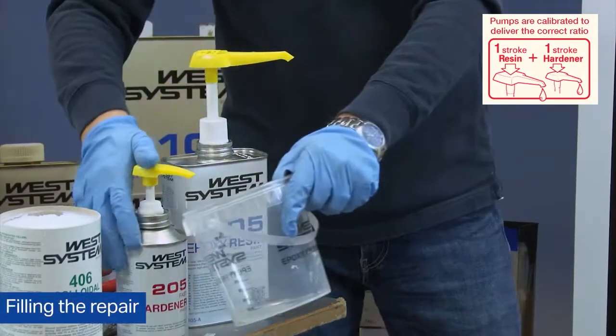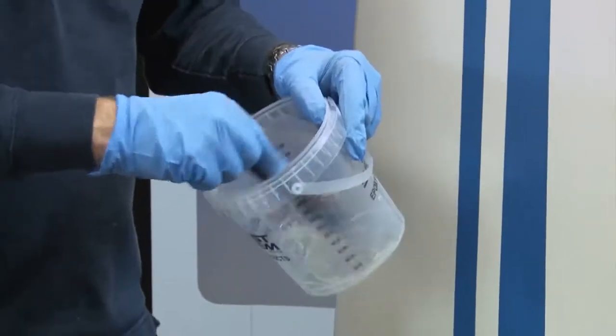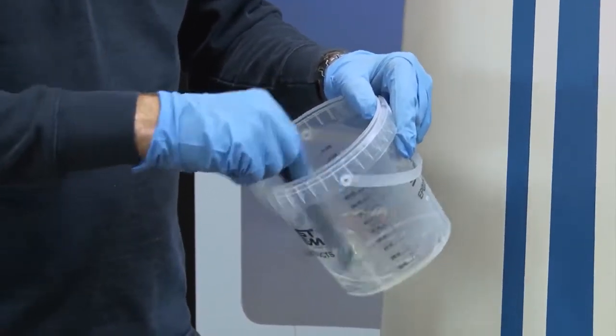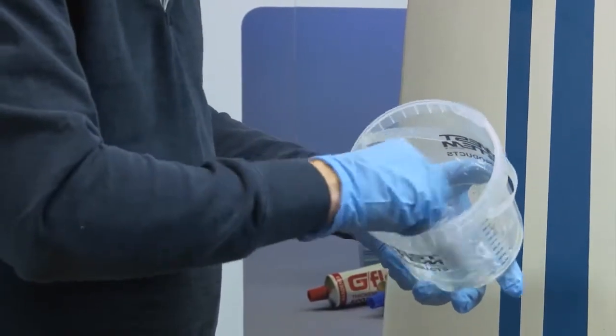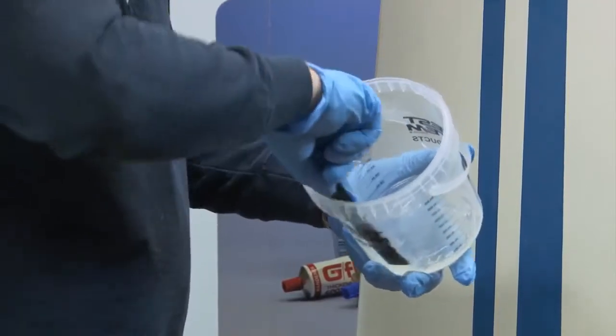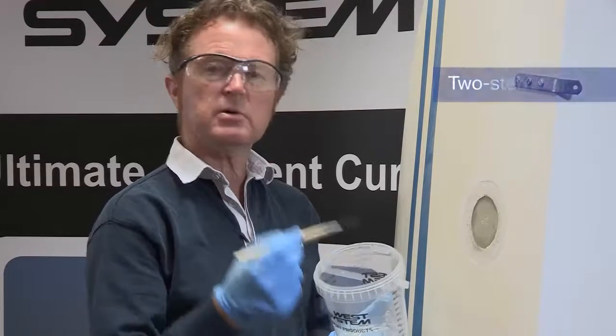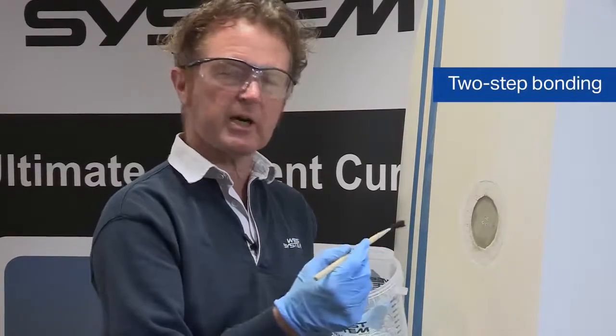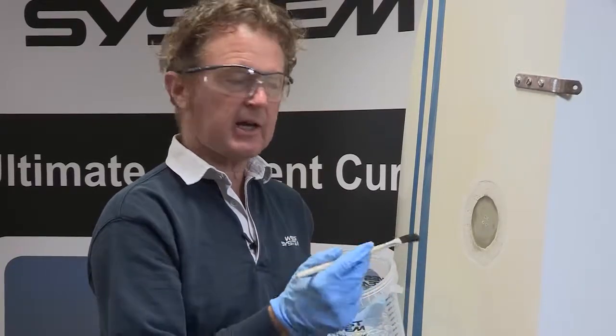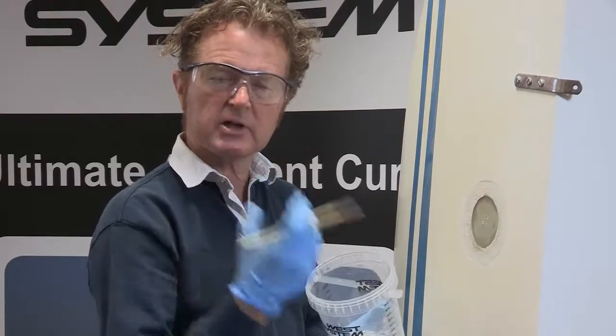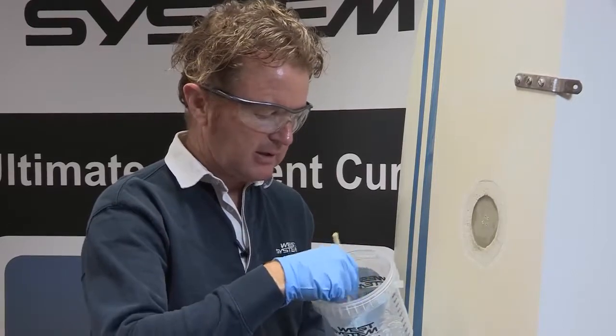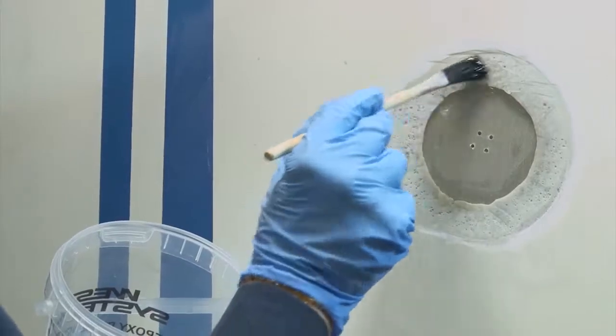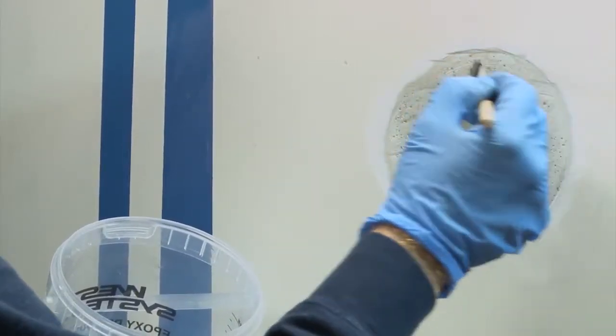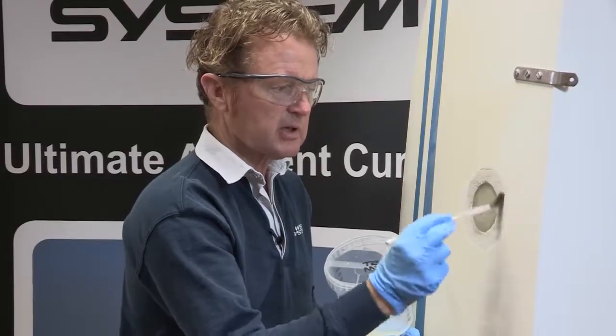So I've used one pump of resin and one pump of hardener to give me enough material to prime the surface here. And again, I'm going to mix for 2 minutes until I've blended the resin and hardener into a nice homogeneous mix. I'm going to brush the area of this repair. This is part of a process that we call two-step bonding. That's to say that before another operation, you brush the resin hardener mix over the surface, and the porosity of that surface allows the epoxy to really wick into the fibre. So I'm hoping here that you'll see quite a strong colour change to the existing fiberglass as I brush the resin over it. And you can see there is a change in the colour as it absorbs the epoxy resin.